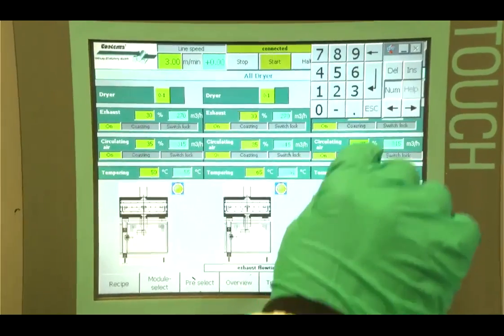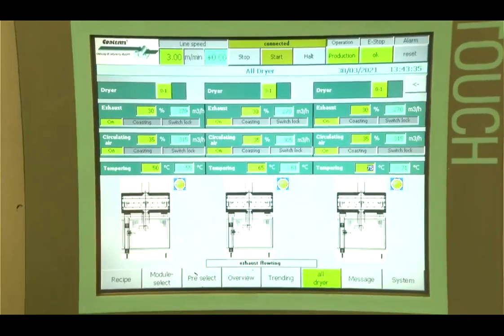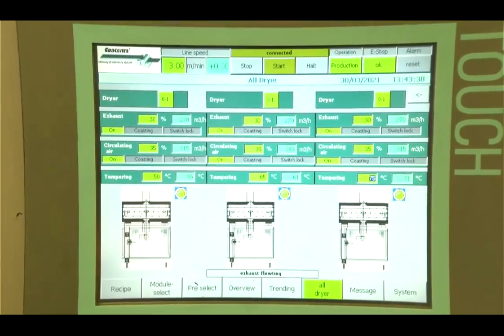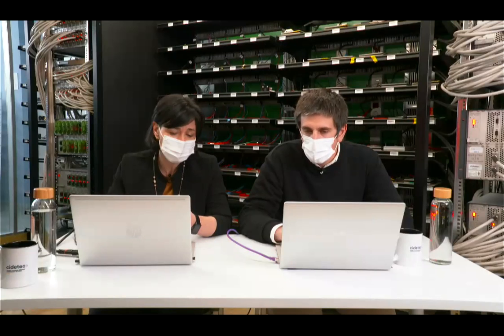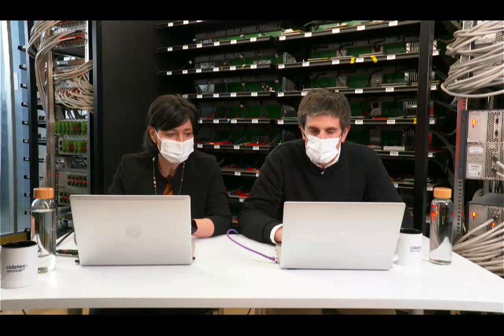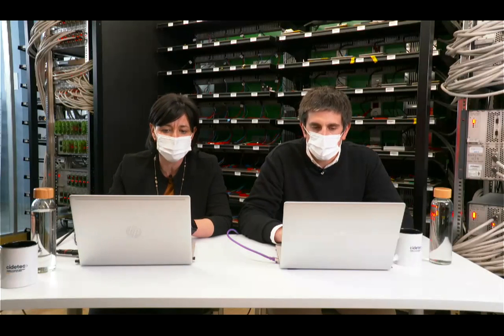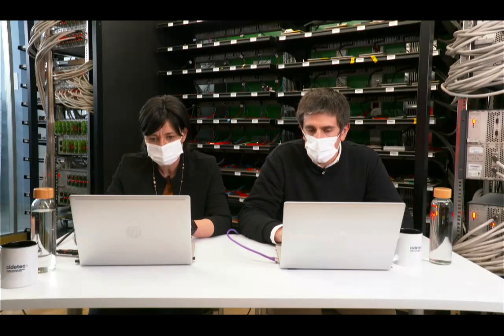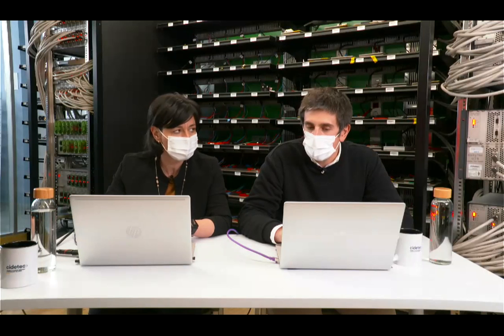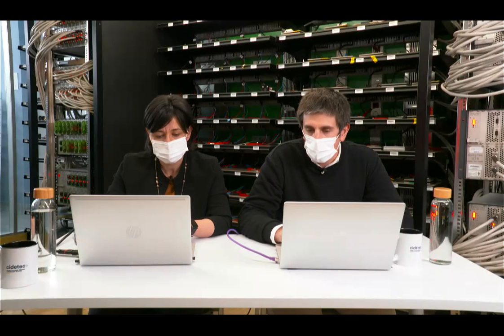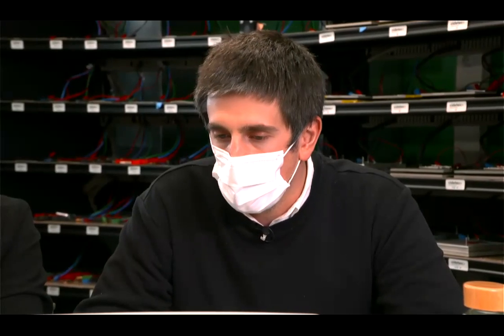Yeah, and what I thought to explain is that this works for both water-based electrodes and for NMP or organic solvents. So with water it will be around 60, 80 degrees, something like that. And for NMP, we have to increase up to 130, 150 degrees. We have to optimize depending on the loading, which electrodes we are producing, and the rate of the drying in the coating machine.